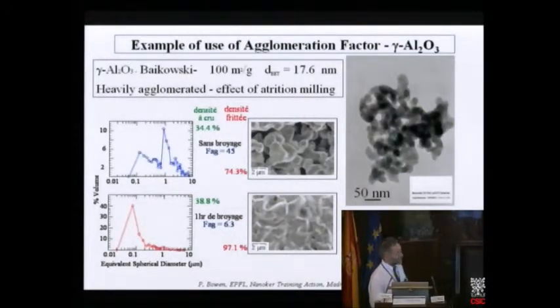After 1 hour of attrition milling, the aggregation factor has dropped to 6.3. You can follow it with a number. We get 97% sinter density, a nicer microstructure. And then if we mill for 3 hours, we can get the agglomeration factor down to 2.5, and we can get the sinter densities up to 99.1%. So basically, you can get there, but you need to get rid of aggregates.